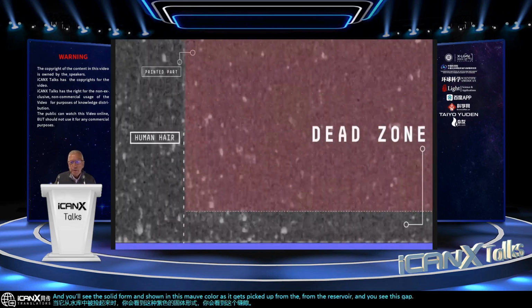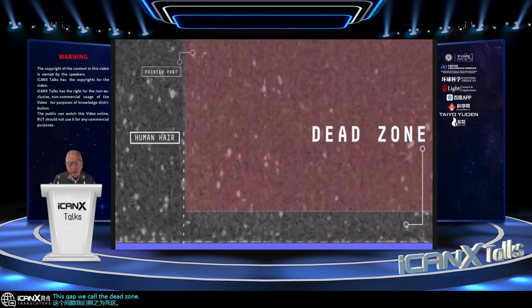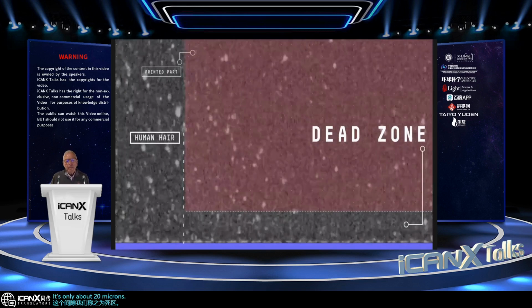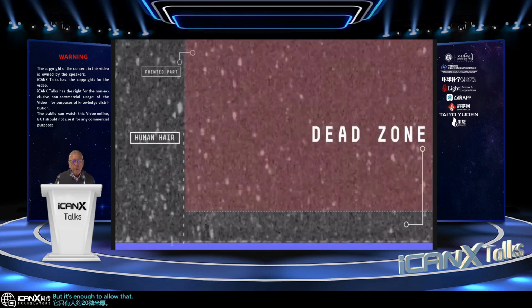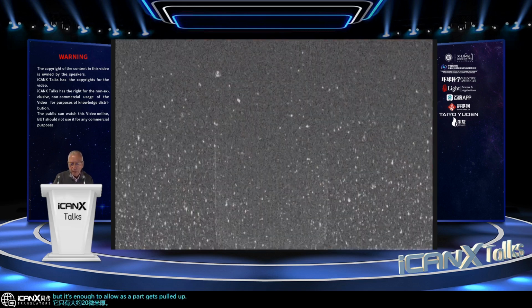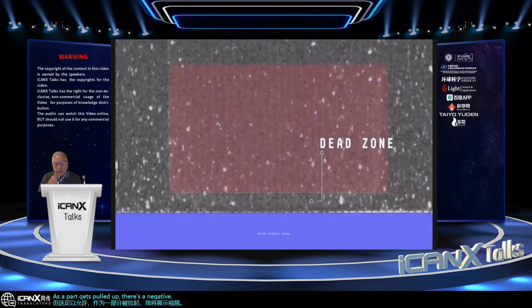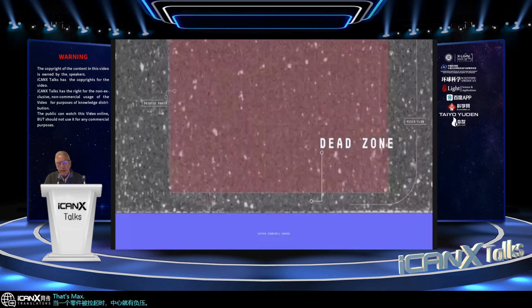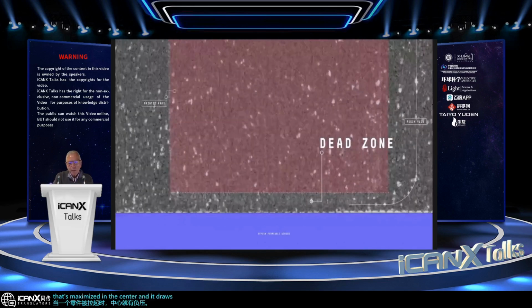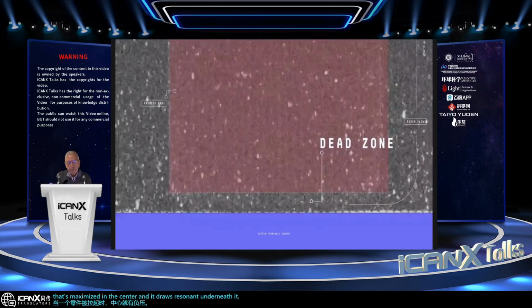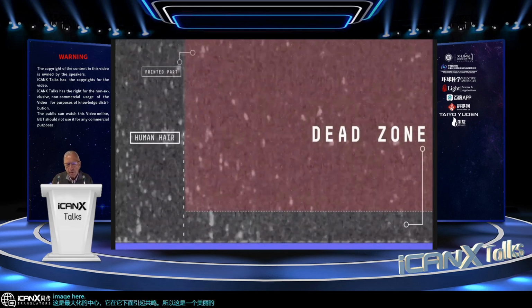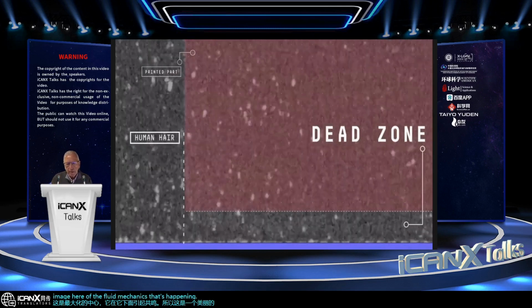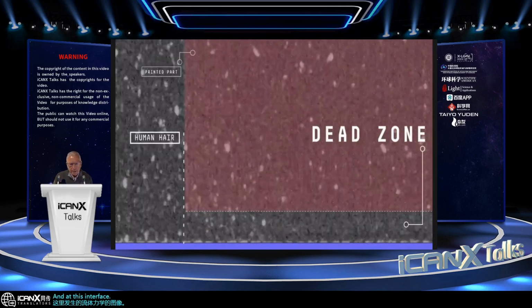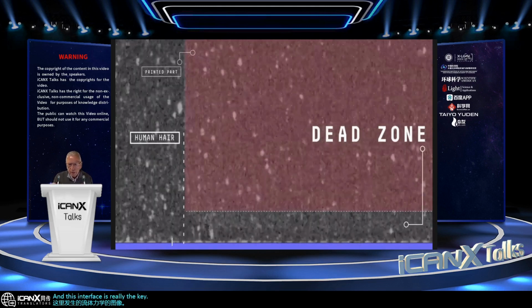This gap we call the dead zone. It's only about 20 microns thick, but it's enough to allow that as a part gets pulled up, I'll show the video again, as a part gets pulled up, there's a negative pressure right at the center that's maximized in the center, and it draws resin in underneath it. So it's a beautiful image here of the fluid mechanics that's happening. And this interface is really the key that allows the 3D printing to go much faster.